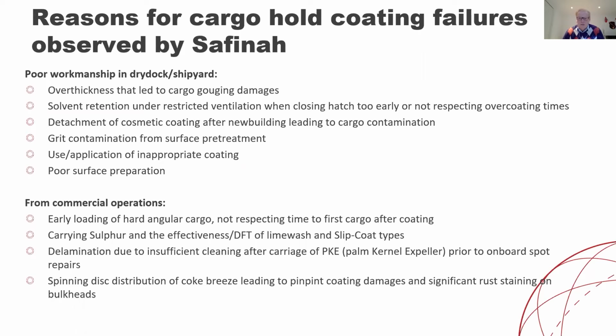recognize that applying the correct dry film thickness is difficult. Ideally, a typical cargo hold coating system is a 2-coat system, 2 times 125 micron is a typical specification, but it is difficult to reach exactly those DFTs, in particular in structures that are complicated and so on. So that can happen quite often. Solvent retention could be, for instance, when you are closing the hatch too early after refurbishing, or not respecting overcoating intervals if it's a 2-coat system.